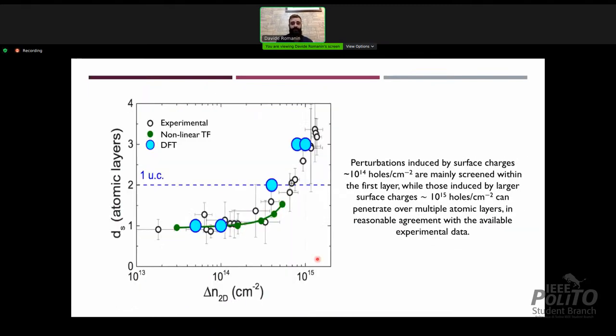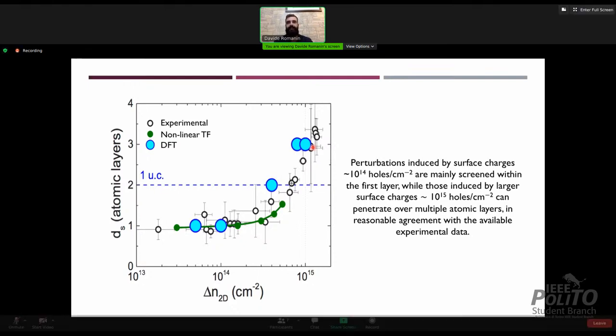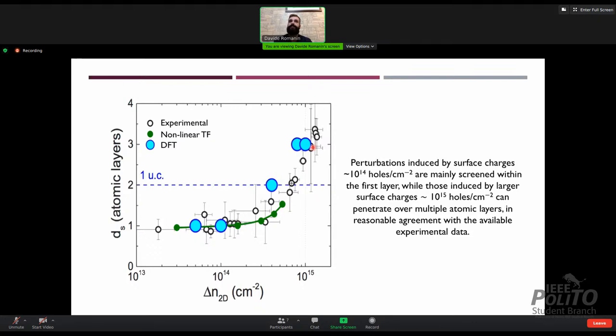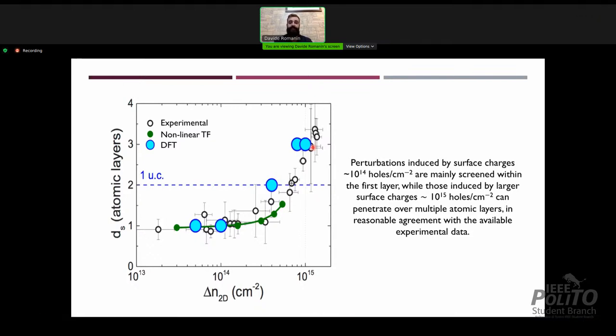So we have tried to compare the experimental results, the black dots, with a nonlinear Thomas Fermi model and with DFT results. We can see that the nonlinear Thomas Fermi results can be used for the moderate, medium doping regime. However, when we go to the high doping regime, the nonlinear Thomas Fermi breaks. On the other hand, DFT results qualitatively describe well the trend of the experimental results. Therefore, we can see that there is an anomalous screening in niobium nitride, and in conventional, phonon-mediated superconductors, that goes beyond the Thomas Fermi approximation.